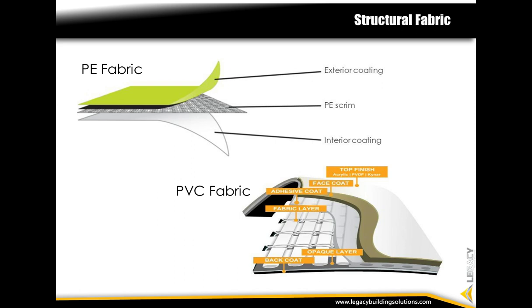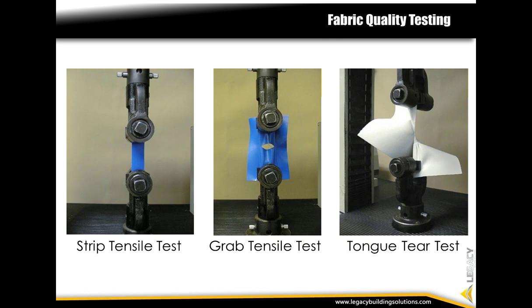Structural fabric is woven from continuous filament polyester yarns. The woven layer of the fabric is called the scrim. The fabric is then chemically bonded with an adhesive coating compound. Finished fabric has limited combustibility and will maintain a brand new appearance for years.